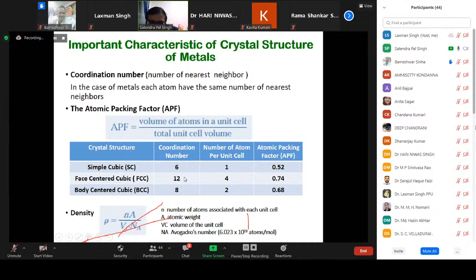Face-centered cubic has a coordination number of 12, 4 atoms per unit cell, and a packing fraction of 74%. Body-centered cubic has a coordination number of 8, 2 atoms per unit cell, and a packing fraction of 68%. From this table, we can say that face-centered cubic is the most closely packed structure. Closely packed means more dense, with a higher packing fraction. We can also calculate the density. It is generally calculated using a formula where n is the number of atoms associated with each unit cell, A is the atomic weight, V is the volume of the unit cell, and N is the Avogadro number. Calculating the density, we can say that face-centered cubic is densely packed because the packing fraction is higher.